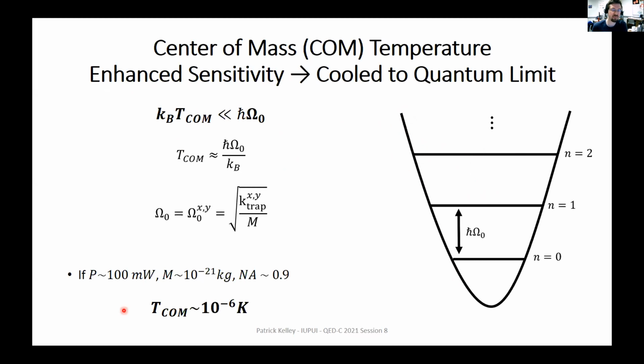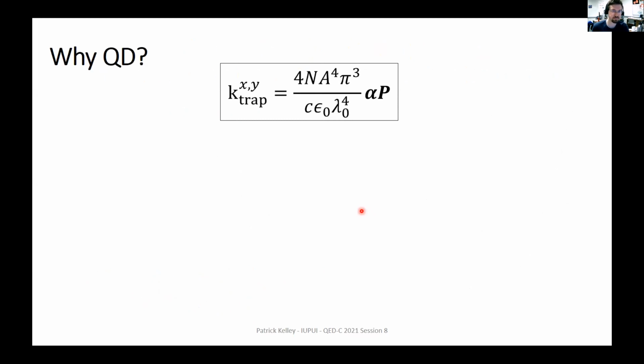what is the effective temperature that we have to get to in such a way that we would be able to start seeing this? And putting in some reasonable parameters of 100 milliwatts, our mass system that we're going to be playing around with a quantum dot, and a very high numerical aperture lens, we're getting something in the microkelvin regime. So we have to cool this particle down to microkelvins.